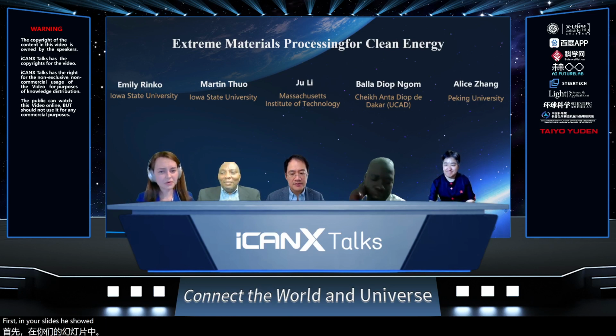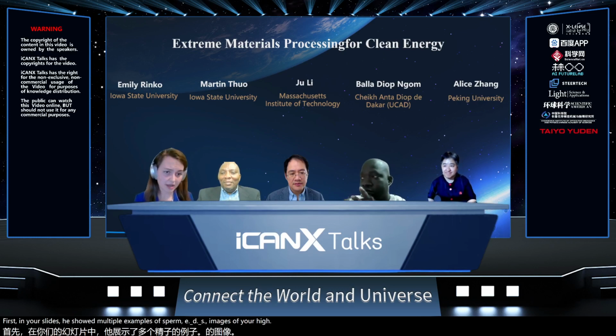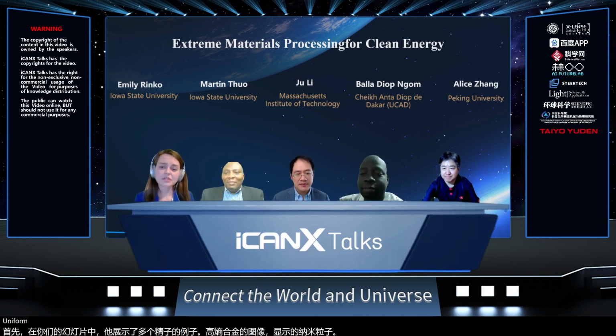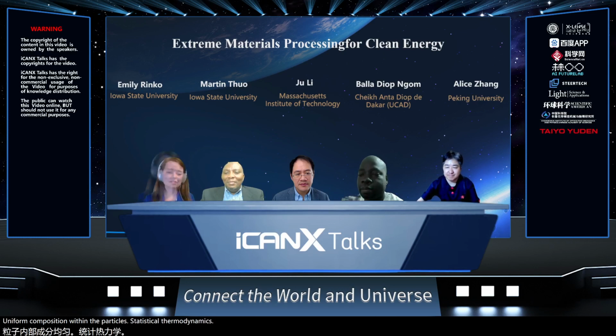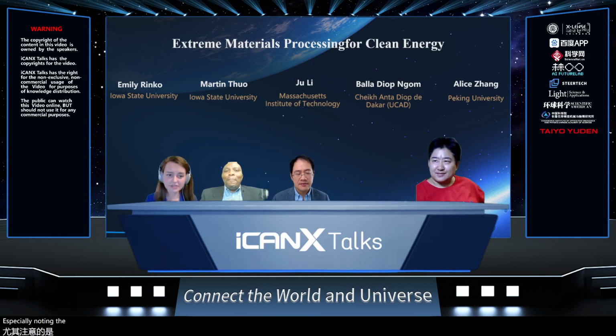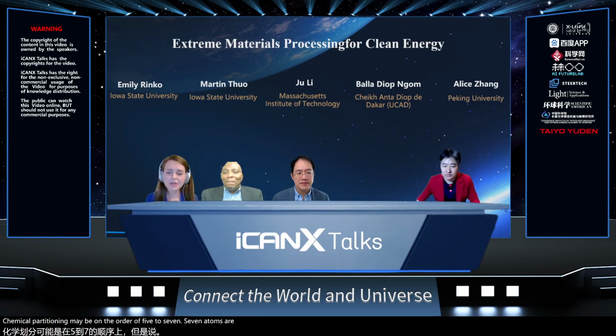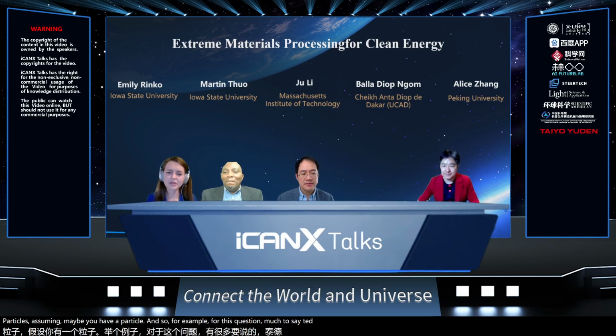First, in your slides, you showed multiple examples of STEM EDS images of your high entropy alloy nanoparticles that displayed uniform composition within the particles. Statistical thermodynamics is certainly suggesting that overall the high entropy nanoparticles are stable and have a uniform chemical composition, especially noting your success of the catalytic performance. But I want to dive a little bit deeper into the details here. I was wondering if you're getting a minor degree of chemical partitioning, maybe on the order of 5 to 7 atoms or so in these high entropy particles, assuming maybe you have particles of, for this question, let's just say 10 nanometers. If you are not having that chemical partitioning on that small range, how does your thermal shock synthesis process assure absolute chemical uniformity?